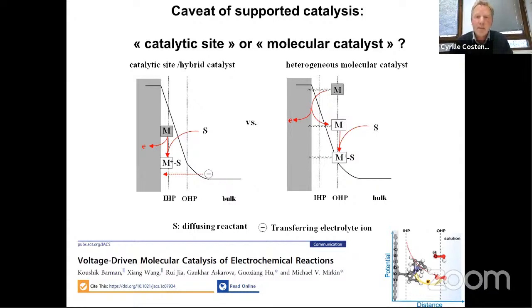One is that if you have a linker which is large enough, this means that your molecular catalyst will be, let's say, away or in this outer Helmholtz plane of the double layer. So you will actually have a catalyst that will behave as if it were diffusing and pick up electron at the electrode, okay? Just that it's not diffusing, it's just picking electron in an outer sphere manner here, okay? So you have heterogeneous molecular catalysis.